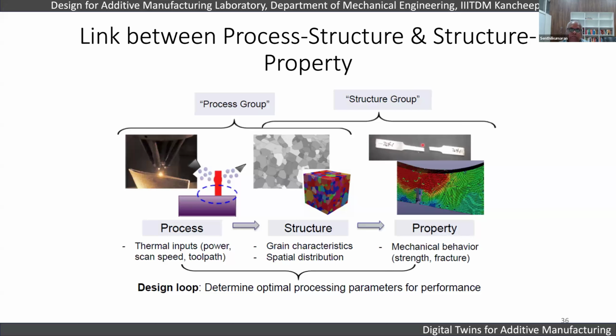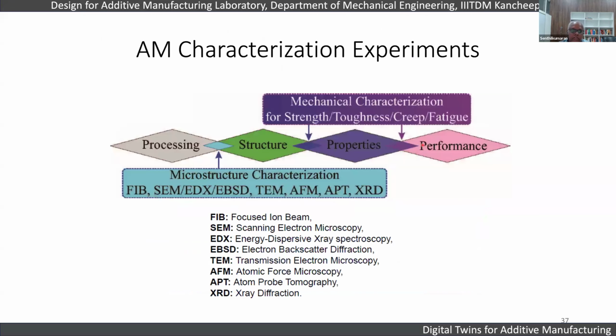So a lot of experiments are also needed while you get these results. For example, sometimes you may not get the result that you want. Your residual stress predictions may not be proper. So you need to use a lot of characterization techniques. For example, we need to use a lot of microstructure characterization and mechanical characterization for strength, toughness, creep, fatigue. For microstructure, we have to use SEM, EDS, EBSD, TEM, AFM, and XRD and all.